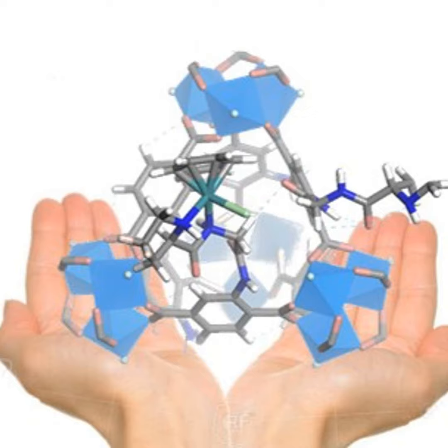Think about those Velcro strips. One little hook and loop by itself is not that strong. But get a whole bunch of them together, and suddenly it's really hard to pull apart. So these interactions are like the molecular equivalent of Velcro. Small but mighty when they all work together. That's a great way to put it. And the DFT calculations showed that these interactions were happening between the reactants and the MOF linker itself. So the MOF wasn't just a passive scaffold, it was actively participating in the reaction through these subtle forces. Exactly. And those weak interactions were enough to nudge the reaction in a completely different direction, leading to the formation of that other enantiomer.